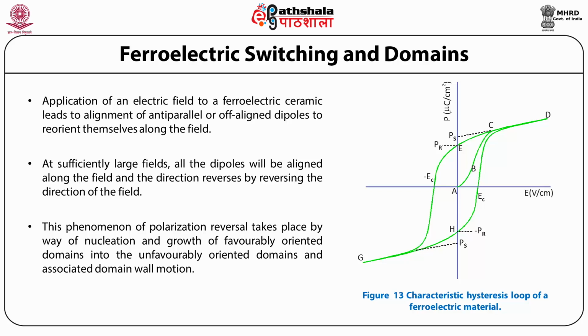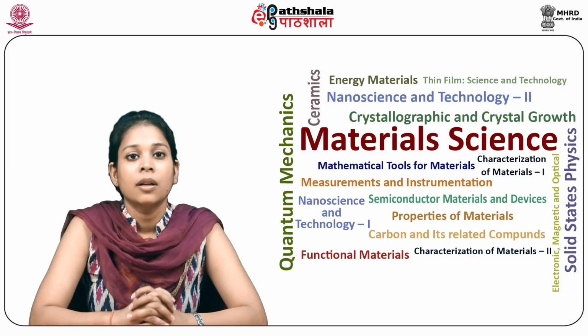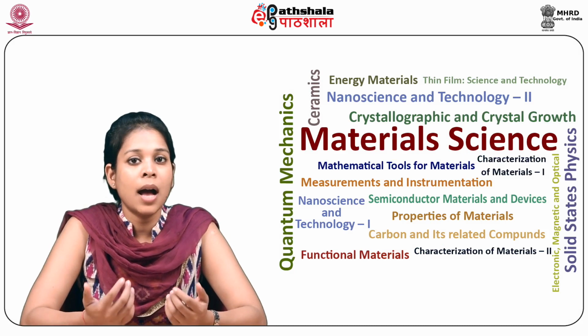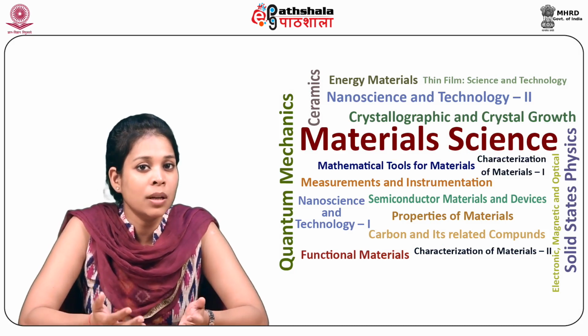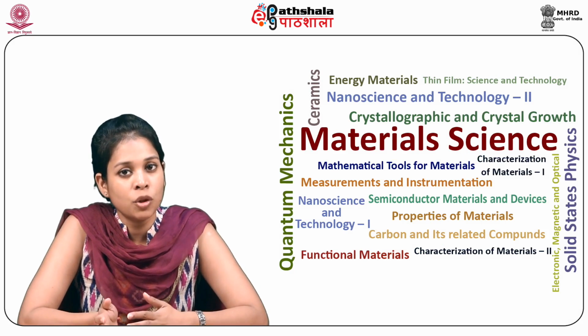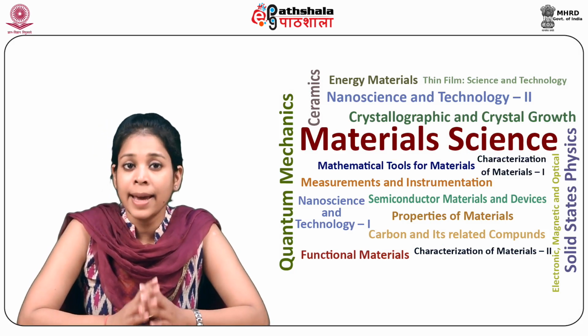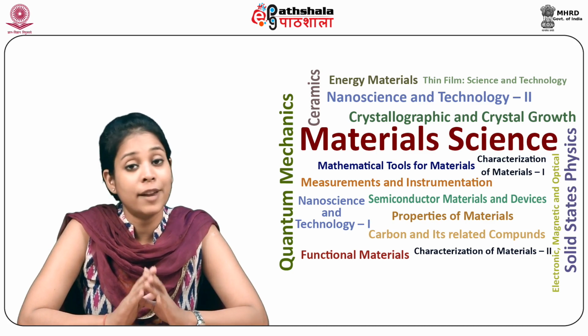So students, you can see this type of behavior in the plot shown, which shows the characteristics of the hysteresis loop of a ferroelectric material, where the electric field is on the x-axis and the polarization is on the y-axis. You can see the value of remnant polarization and the saturation polarization along with the coercive fields. If we assume that our hypothetical crystal has an equal number of positive and negative domains in the virgin state, then the net polarization of the crystal will be 0.